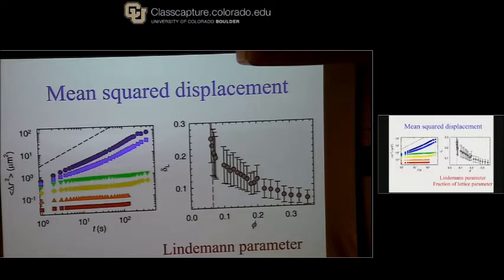And the reason for this is you're just preventing melting. You're making the particles hotter and hotter. So they're fluctuating more and more, but you're not allowing them to melt because there's no interface. So here shows that the Lindemann parameter, when it melts, is getting really high.